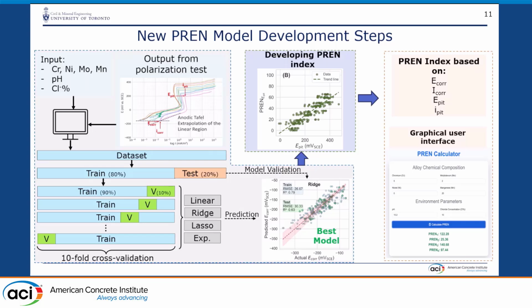By the way, we tried this on literature data, in case you're wondering, but at the moment it is very erroneous. So we're going with our experimental data. What we did was perform a potentiodynamic polarization and got the data from there, which is the curve you can see at the top there. Our input parameters were focused mainly on chromium, nickel, molybdenum, and manganese, as well as pH. We varied the pH and the chloride content as well. So we took that data set and put it into some regression models in machine learning, and then we developed a PREN index based on that, and a user interface that people can use.